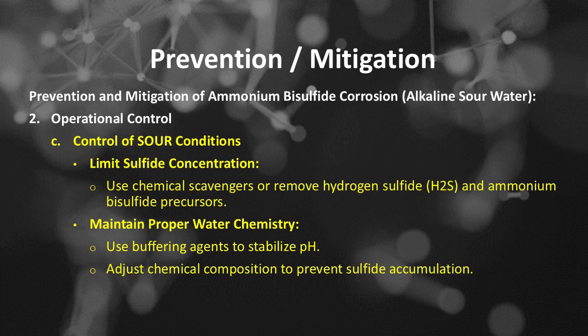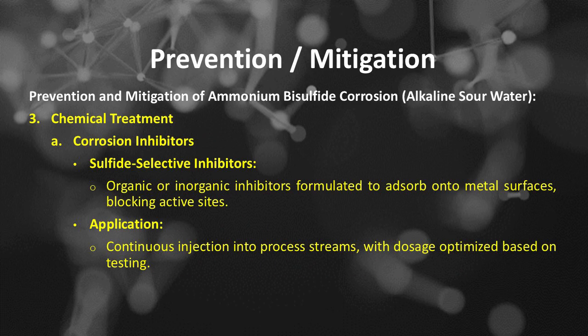Operational control. Number C is control of sour conditions. Limit sulfide concentration: use chemical scavengers or remove hydrogen sulfide, H2S, and ammonium bisulfide precursors. Maintain proper water chemistry: use buffering agents to stabilize pH, and adjust chemical composition to prevent sulfide accumulation. Prevention and mitigation of ammonium bisulfide corrosion in alkaline sour water.